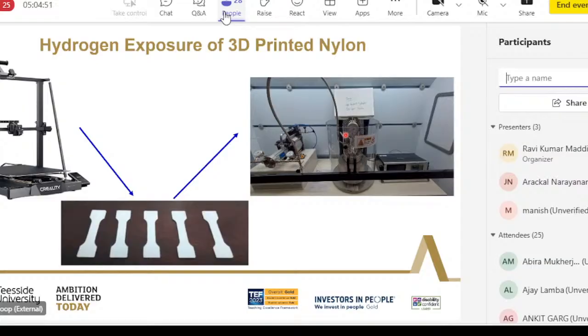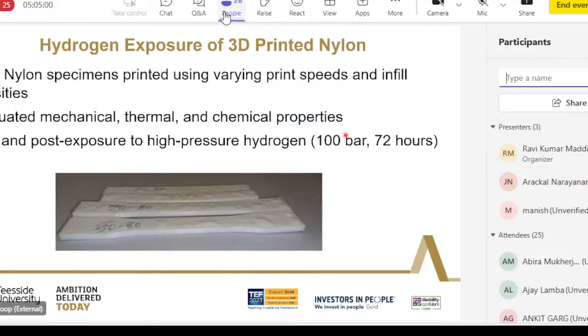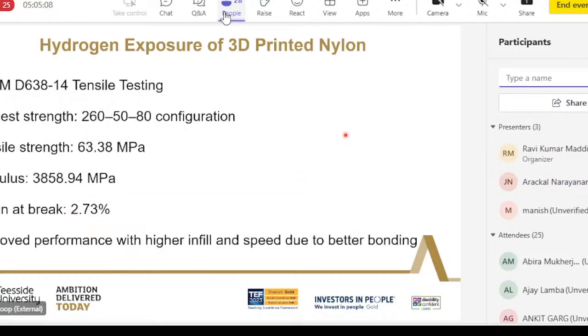It's part of an ongoing project on exploring different polymers. This sideline project is on exploring how 3D printed nylon can also fit into this role. We exposed it and could see this swelling behavior, and again, we could see a lot of impact on the mechanical properties. This is the configuration that we use: 260 is the printing temperature, 50 is the printing speed, and 80 is the infill density, 80%. And this is the typical tensile strength, modulus and strain at break for the conventional nylon parts.